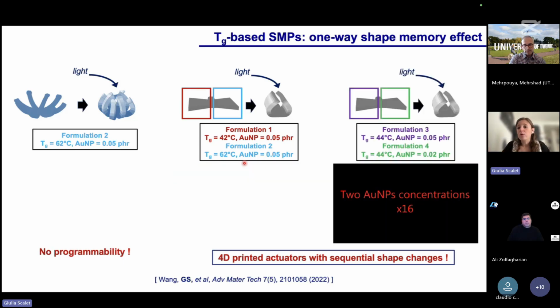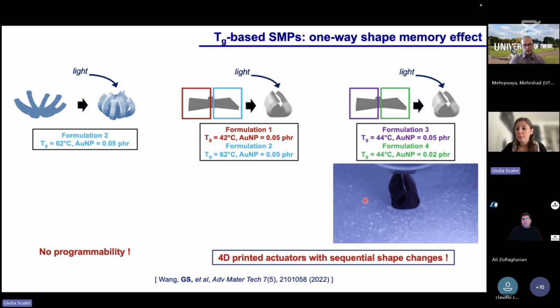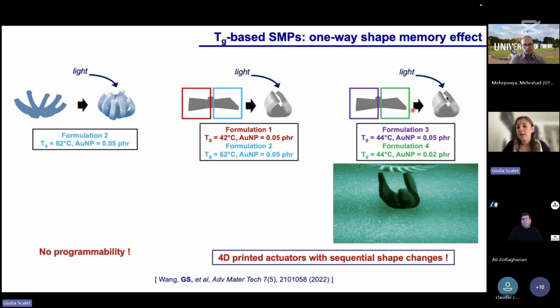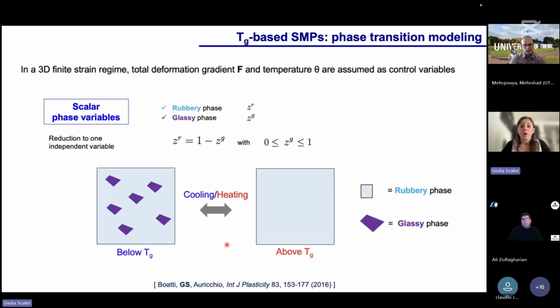And you can also play, again, with different polymers, but with the same chemical composition, so the same glass transition temperature, but you can use a different content of gold nanoparticles in order to achieve a differential heating, so a different heating upon light irradiation that allows to achieve again sequential shape changes and sequential shape recovery upon light irradiation. So you have different approaches that you can exploit in order to achieve programmability also with the one-way shape memory effect. You can model.